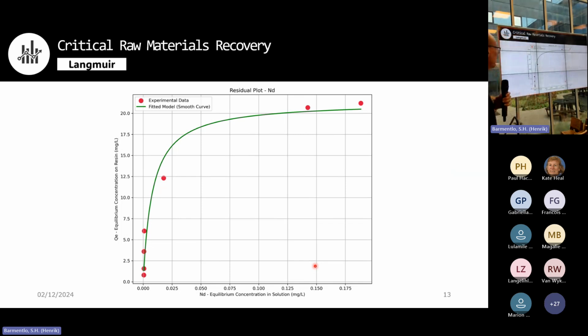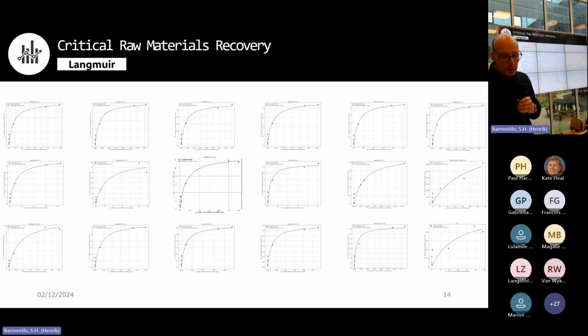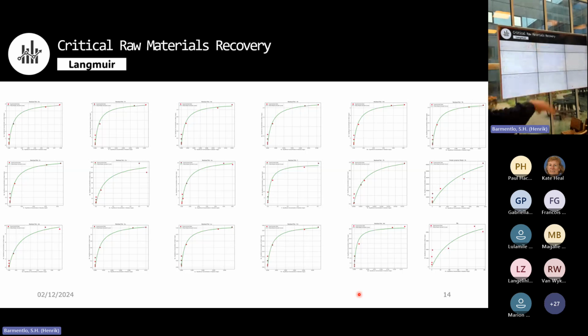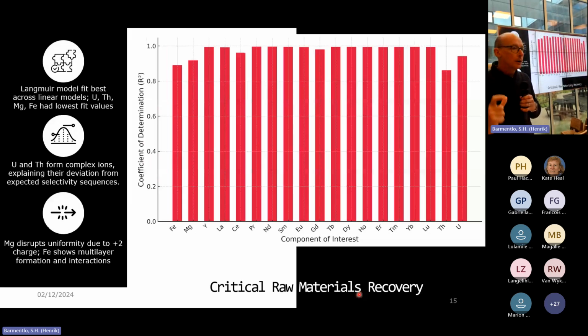So this is the residual plot for neodymium, I think. And that's your equilibrium concentration on the resin, and this is your equilibrium concentration in solution. So what this will tell you is how quickly you get from solution into your resin. And what's more important is we did that for everything. So you don't need to worry about those, but just to show you, we did them for all 17 of those compounds, as well as for iron and magnesium. And then we had a look at how good was the fit?